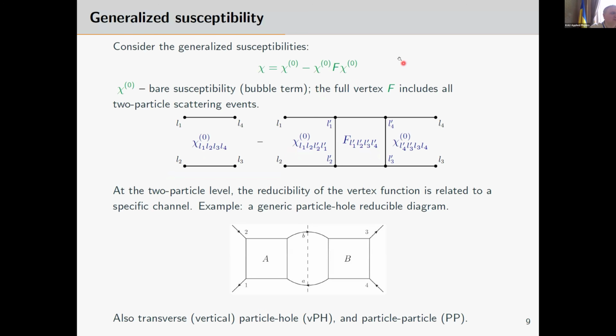How do we treat normal state instabilities? Let me again remind theoreticians of the basic problem from the Abrikosov-Gorkov-Dzyaloshinskii textbook: in superconductivity, we have interaction in the Cooper channel and an infinite set of diagrams, which shows that electrons create Cooper pairs. This is when we consider the normal state. And this is where the generalized susceptibility is calculated. In superconductivity, we restrict ourselves just to superconductivity, but I should remind you that the situation in different channels of superconductivity can be more tricky: S wave, D wave, P wave, and so on. Here we have all possible instabilities, including magnetic.